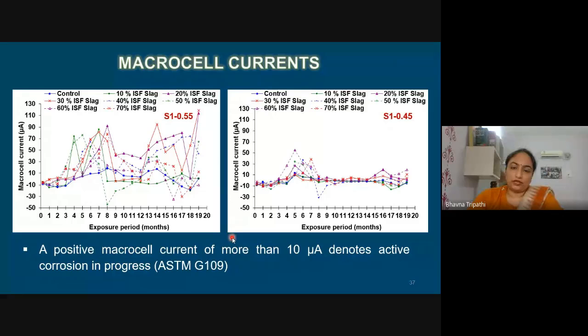We measured three kinds of observations to monitor corrosion. One was macro cell current, the other was half cell potential, and the third was the corrosion rate. Macro cell current and half cell potential are both performed on specimens by connecting anode and cathode. We get the macro cell current, and this was conducted as per ASTM G109. You can see very abrupt changes in the current, which is normal because corrosion is an electrochemical activity going on inside concrete. It measures that.